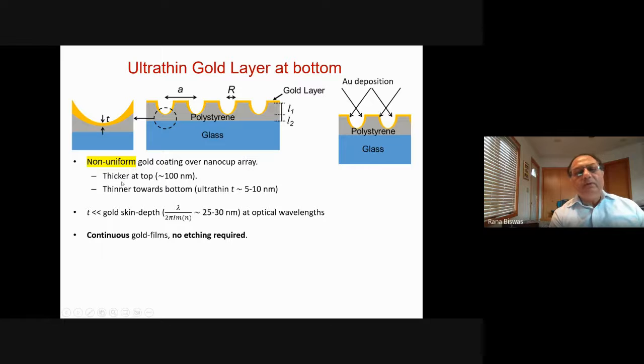But if you look more closely, the gold coating is non-uniform over this array. So it's quite thick at the top, about 100 nanometers, but considerably thinner at the bottom. We estimate it's ultra thin, just about 5 or 10 nanometers at the bottom of this nano cup over here. And this thickness is considerably less than the skin depth of gold, which is 25 or 30 nanometers at optical wavelength. So what we have done, we have made a continuous gold film without any etching.